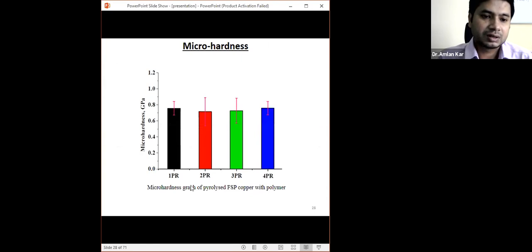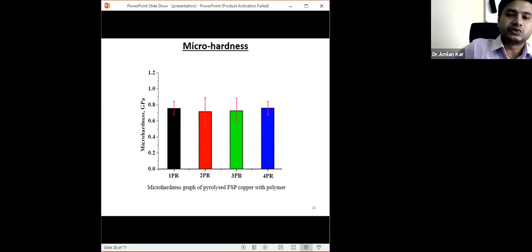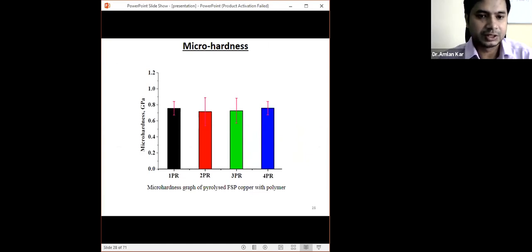And after the pyrolysis, you can see there is no change in the hardness. Why is there no change in hardness? Because of the availability of a high fraction of pores in the composite. Because of the high fraction of pores in the composite, during the hardness test or during the indentation, it does not resist the indentation load because of the pores available in the composite, and therefore there is no increase in the hardness.